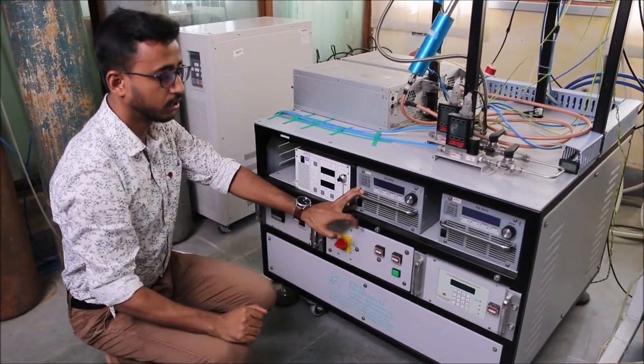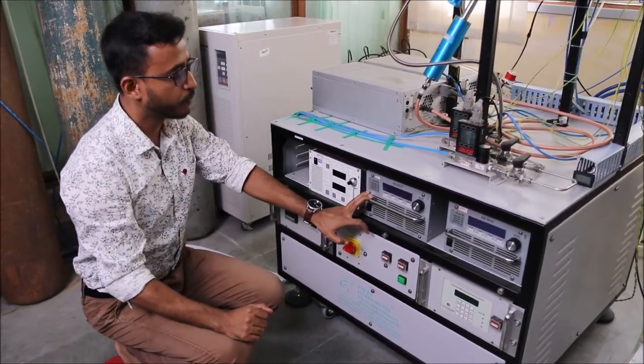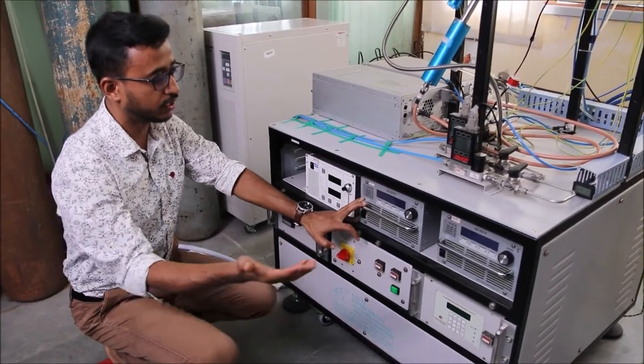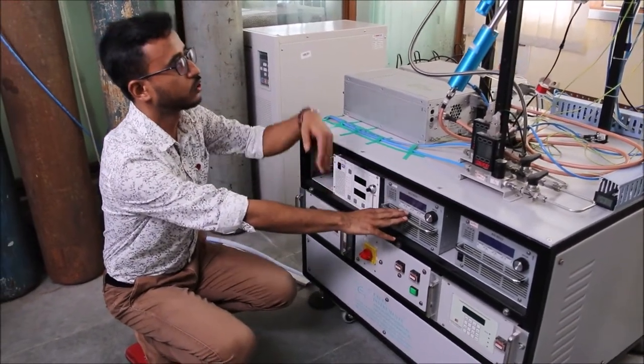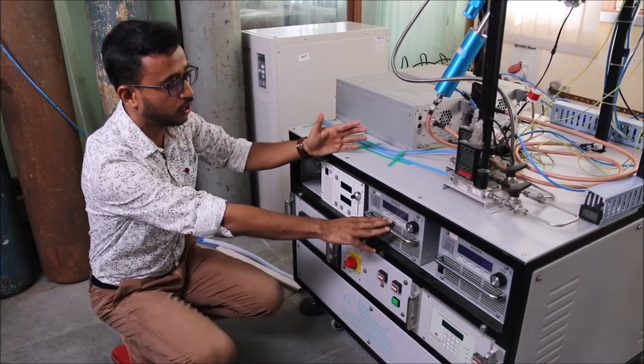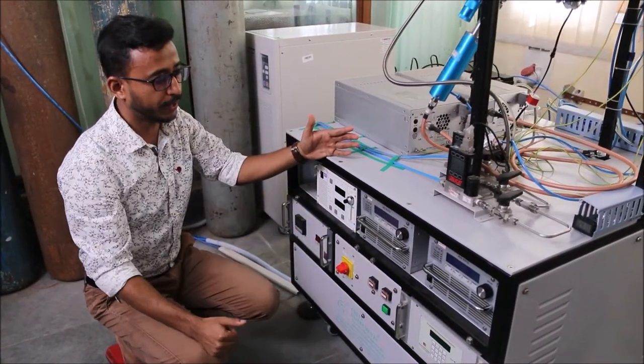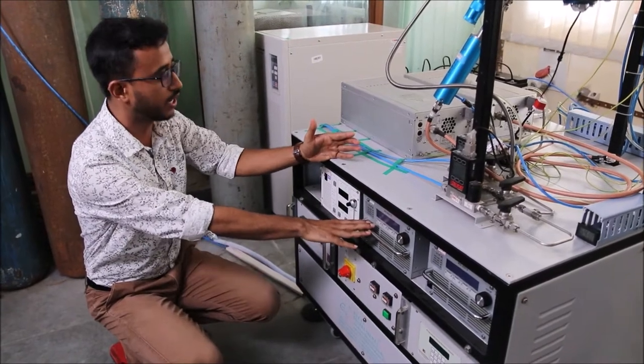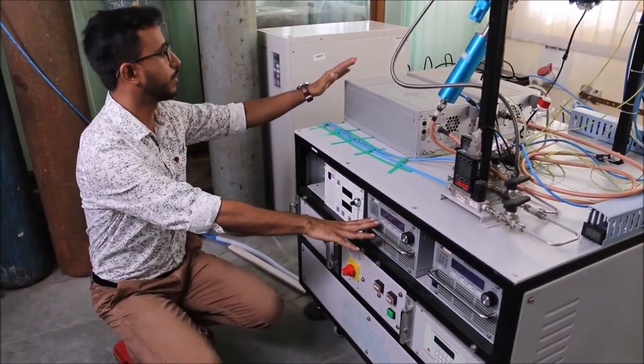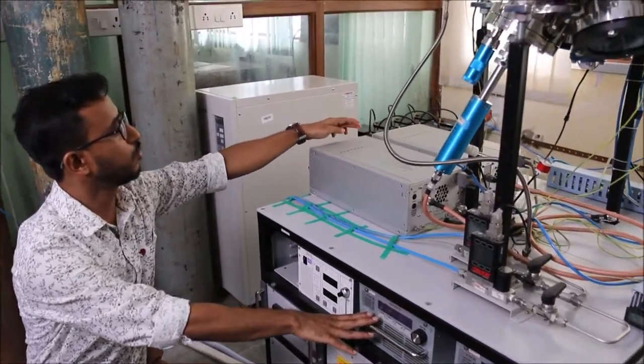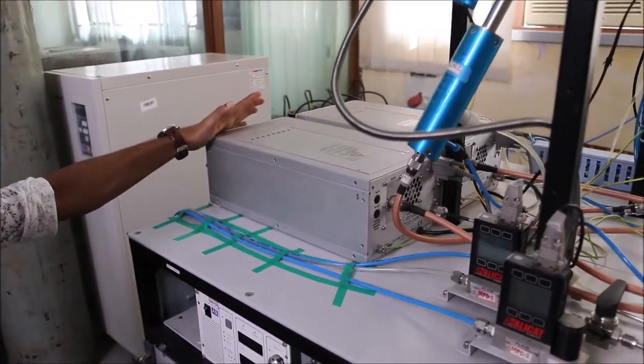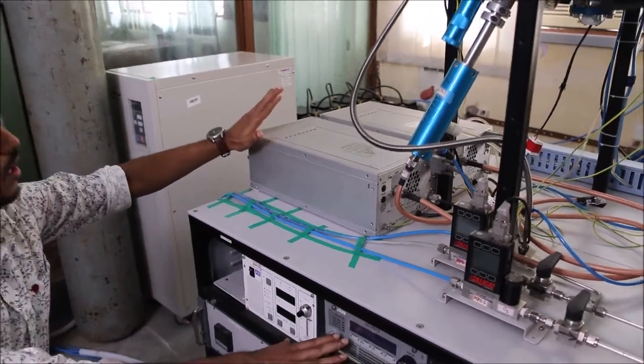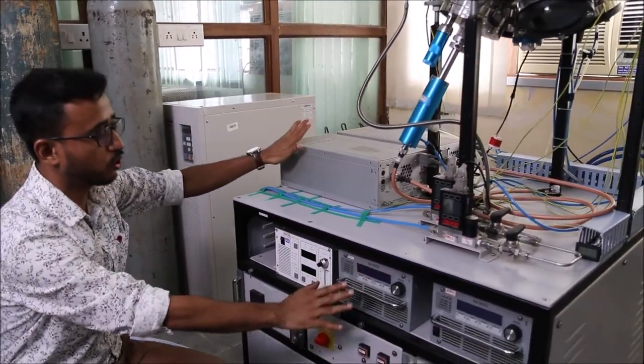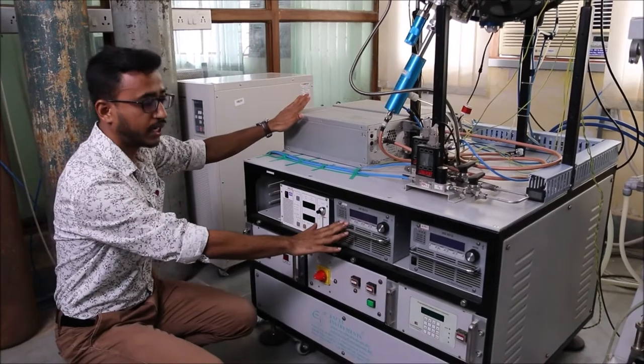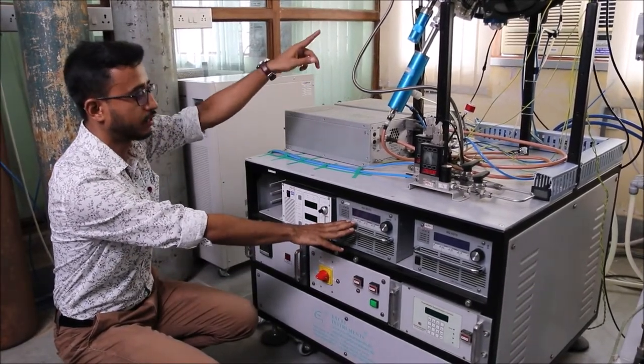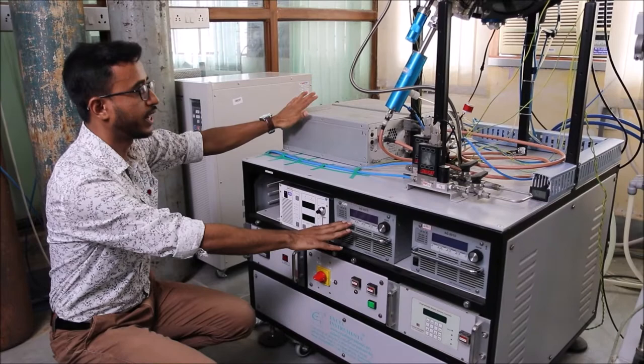We use 13.56 megahertz of frequency, and because at that frequency the power cannot be directly transferred to the output or to the load because of the mismatch of the impedances, we need to connect a matching network. So this is placed at this part. We have two matching networks for these two RF sources. What it does is it matches the impedance of the target with the source of this power, so that the maximum power can be transferred from the source to our target or the load, and we won't get any reflected back power.